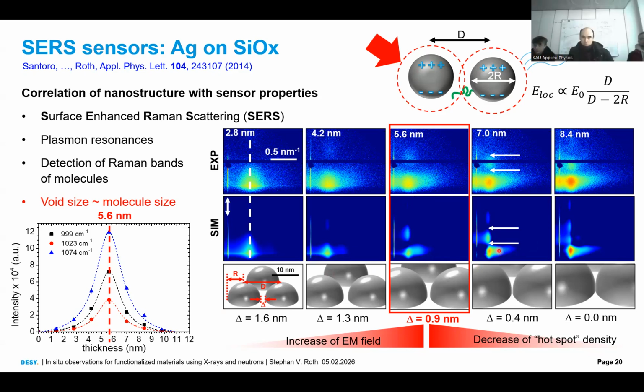Yeah, so this is, as I say, very powerful. Even without telling me, I made this. We made this, and we were deliberately not told what it was. I always tell industry, if you tell us, it's faster, but we can derive the material inside from this, and we can tell you really when the clusters make a percolated layer. In addition to this shifting here, we can calculate this 2R/D ratio.